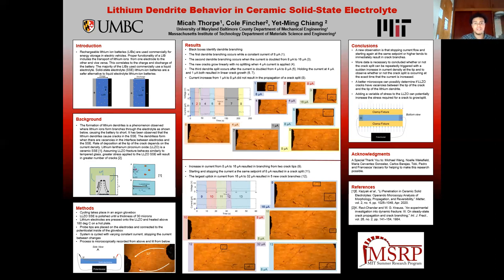Let's see the first video clip. The first dendrite branching occurs when a constant current is applied. And this is not necessarily what we expected. What we expected is what we see in figure 3, where when we increase our current, there's a branching in the dendrite. And then we drop back down to 4 microamps from 16 microamps. And then in our fifth image, we jump to 8 microamps and we get a split as seen here. And that was the last of the splits for this set of cycles.